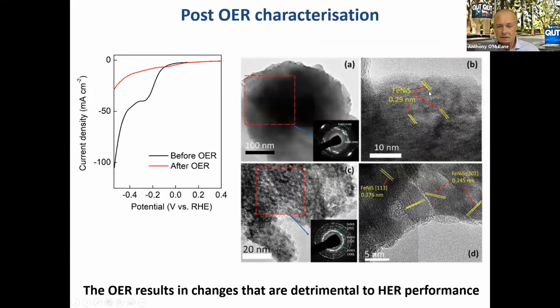So if we look at the TEM, before and after: before, we have quite a dense material, and we can see the phases associated with an iron nickel sulfide species. After the oxygen evolution reaction, it becomes more porous, more crystalline, and we start developing newer phases of the iron nickel sulfide.